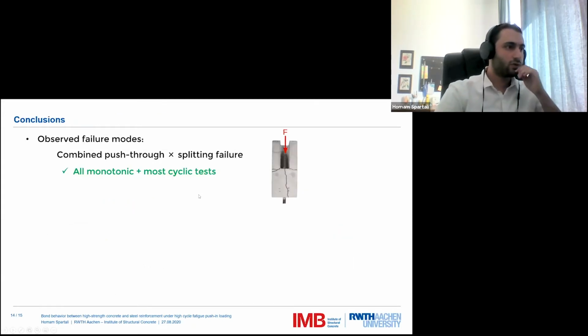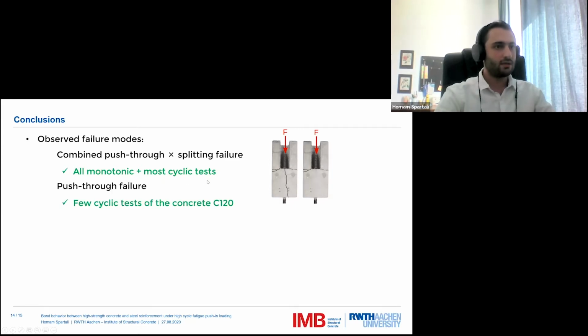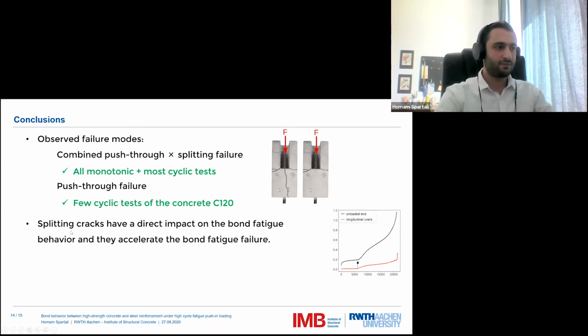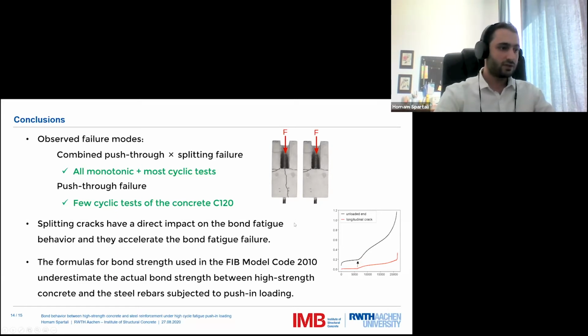So here we come to conclusions. We observed 2 failure modes. The first is combined push-through splitting failure in all monotonic and most cyclic tests. And we observed a pure push-through failure mode in few cyclic tests of the concrete C120. We also noticed that splitting cracks have a direct impact on the bond fatigue behavior, and they accelerate the bond fatigue failure, like we saw in these graphs. Finally, the formulas for the bond strength used in the FIB model code underestimate the actual bond strength between high-strength concrete and steel rebars subjected to push-in loading.